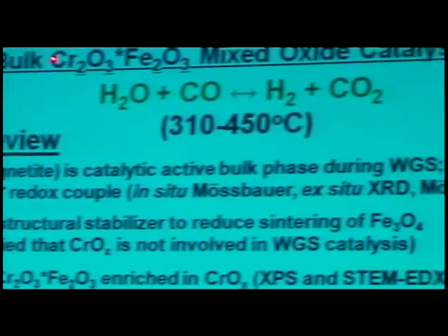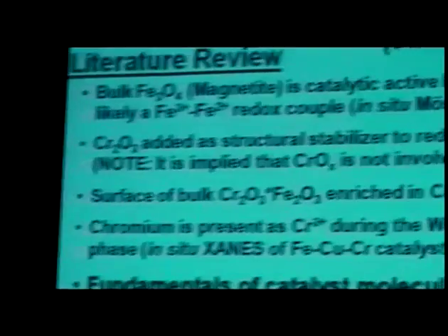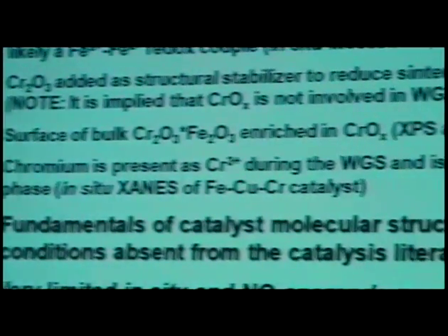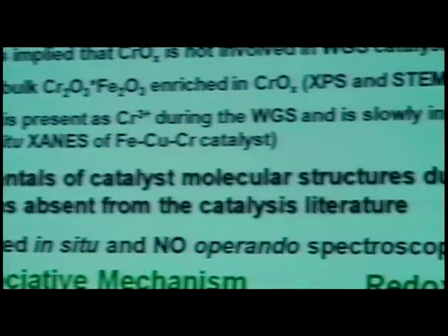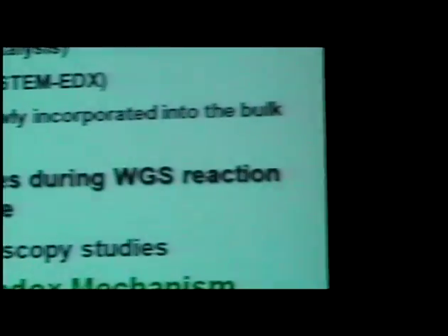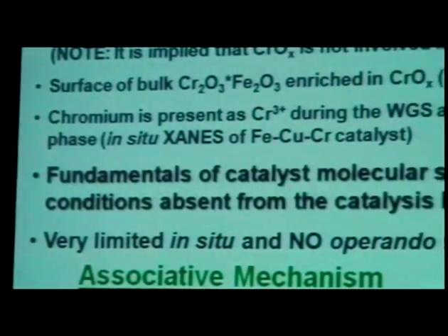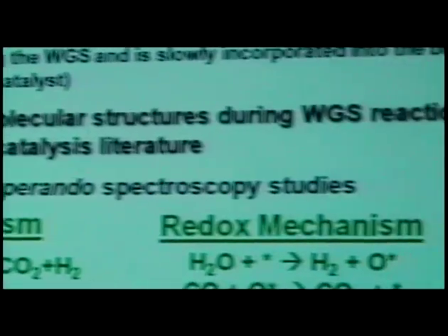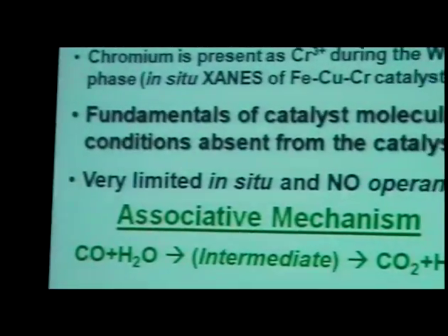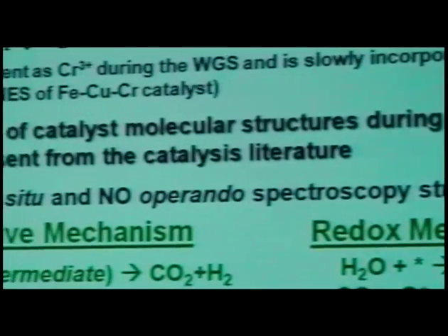So let's look at the literature and the history of the water-gas shift. It's a well-known technology. Originally it's chromium iron. More recently, copper's been added, and as time permits, I'll also talk a little bit about what copper is doing here. So this is the water-gas shift reaction that occurs at these temperatures. It's the high temperature reaction conditions. If you look at the literature, what the literature does agree on is that the iron in the catalyst is magnetite, Fe3O4, and this is referred to as the active phase during water-gas shift.